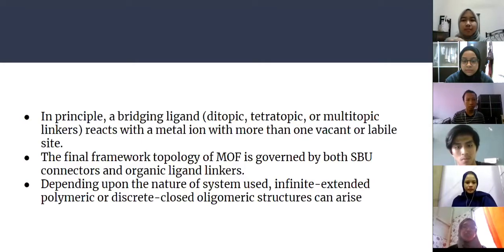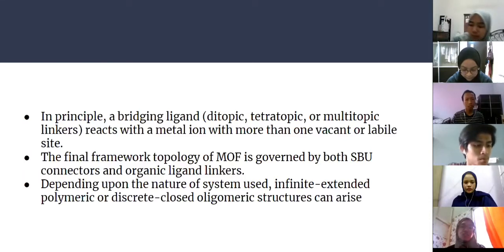In principle, the bridging ligands such as ditopic, tetratopic, or multitopic linkers will react with a metal ion with more than one vacant site or labile site. The final framework topology of MOF is governed by both SBU connectors and organic ligand linkers. So depending upon the nature of the system used, extended polymeric or discrete closed oligomeric structures can be arrived at.